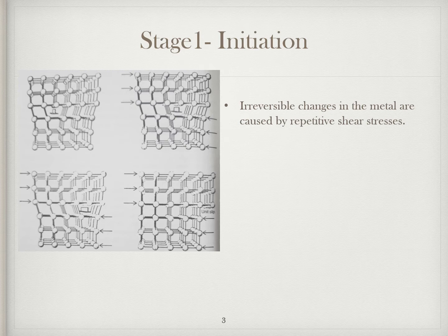The most significant factor about the initiation stage of the fatigue fracture is that the irreversible changes in the metal are caused by repetitive shear stresses. The adjoining figure shows schematically these microstructural changes that occur in the crystal lattice because of the shearing or sliding stresses that are repetitively imposed on the structure. The figure at the top left shows an edge dislocation caused by